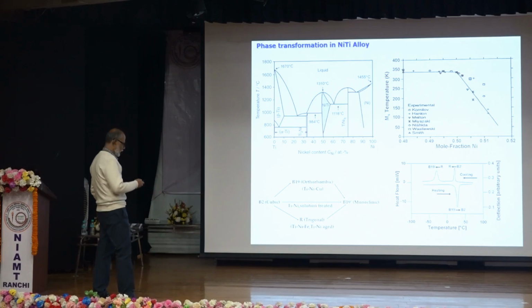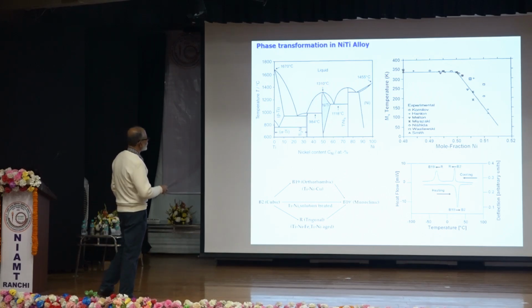And this is nickel titanium alloy. It is basically a 50-50 composition. The nickel titanium phase is an intermetallic phase having 50 nickel, 50 titanium, right? And we have two intermetallics associated with this, Ti2Ni and TiNi3. So any fluctuation from the composition may give rise to formation of these intermetallic phases. And we find that the Ms temperature is very sensitively dependent on nickel content after 50%. So if there is any fluctuation in nickel content above 50%, the Ms temperature changes drastically. As such, in 50-50 composition, the Ms temperature is 63 degrees centigrade.